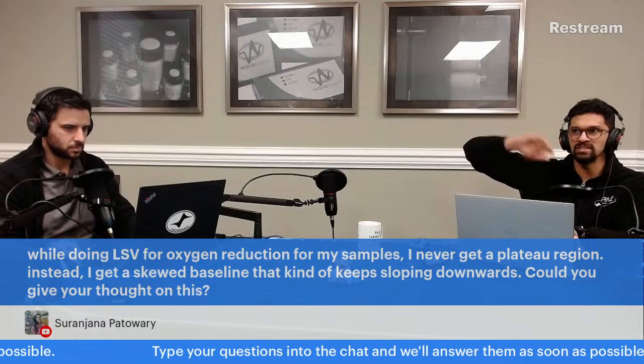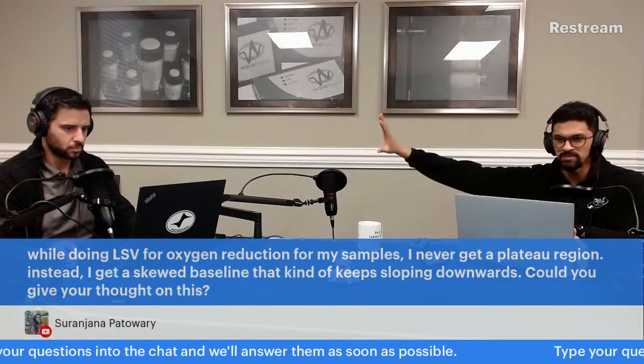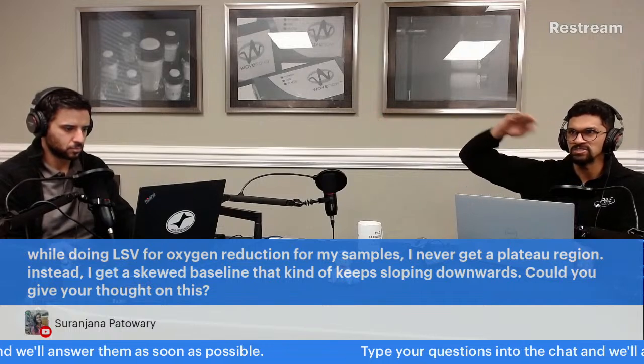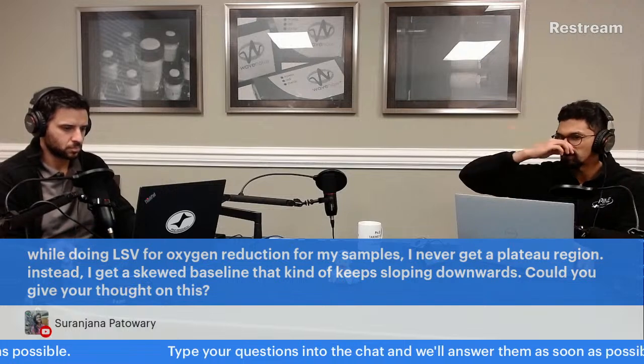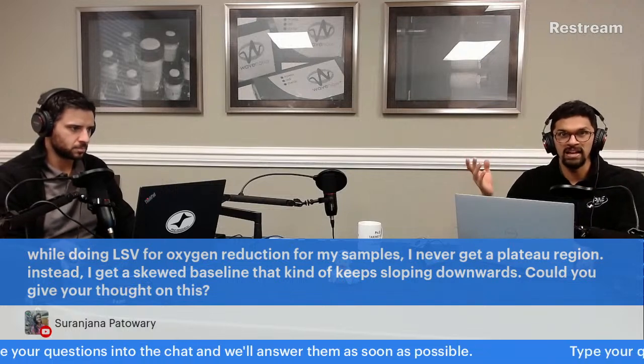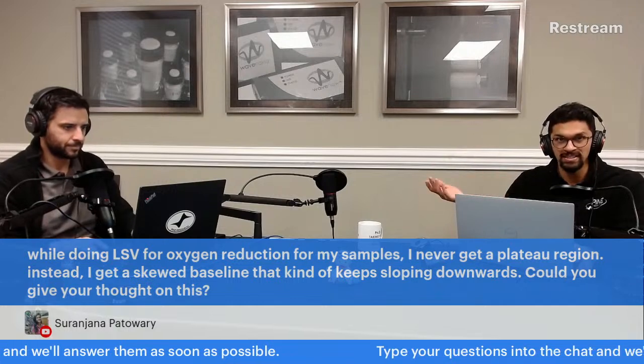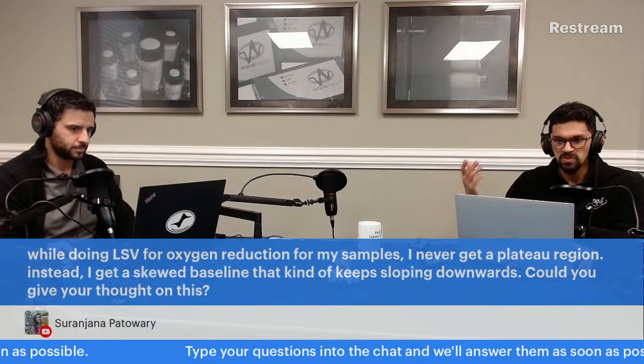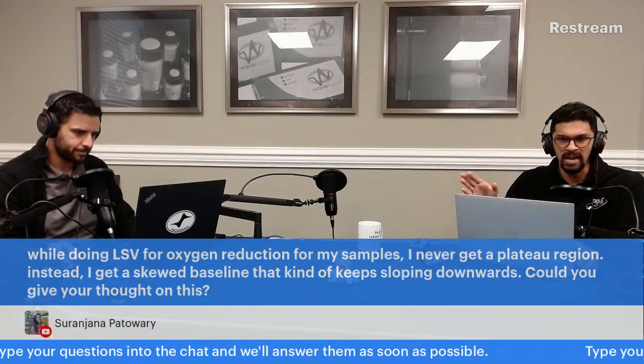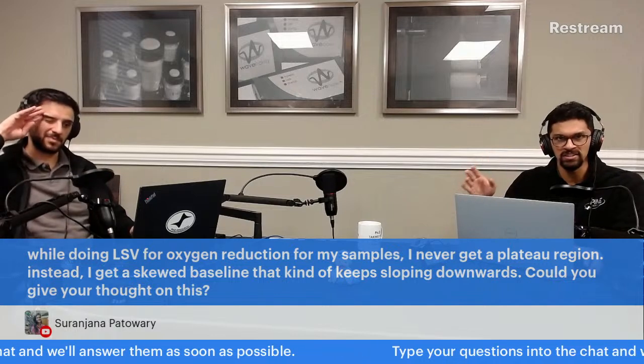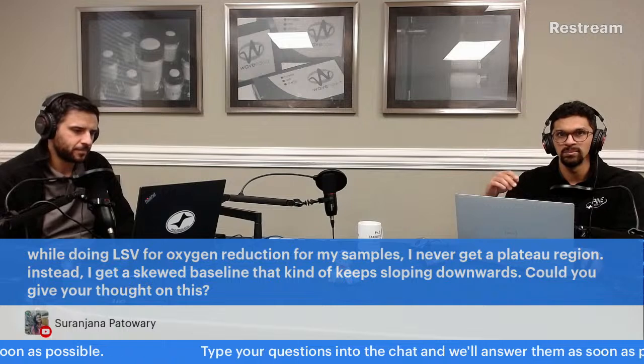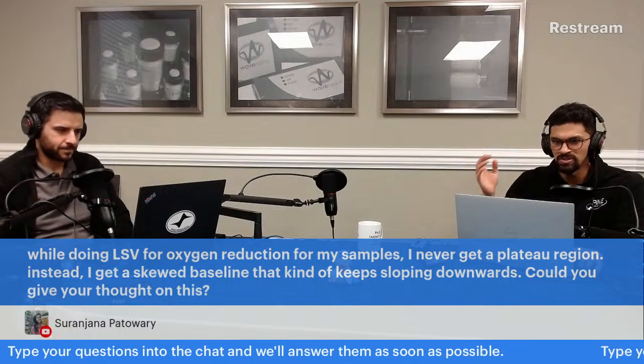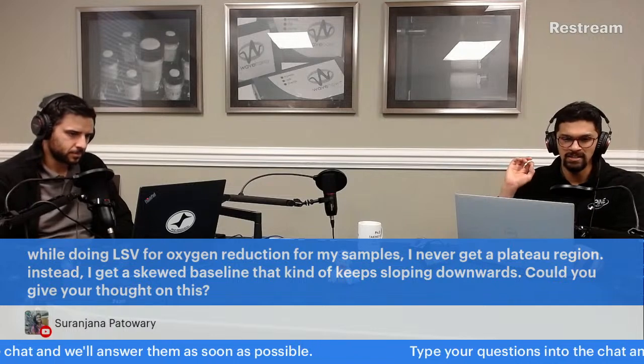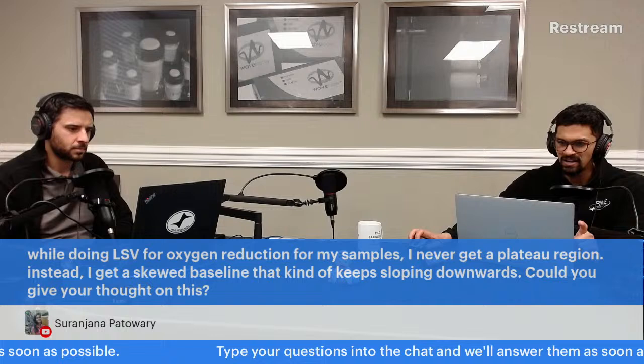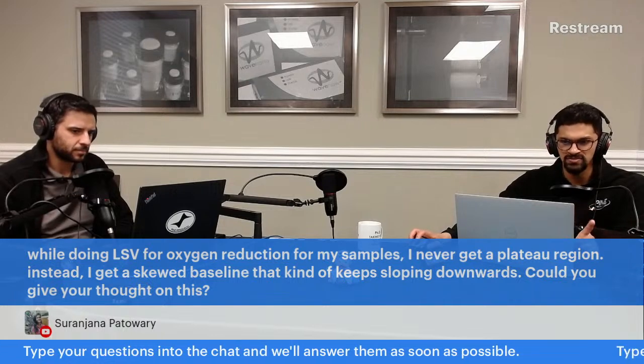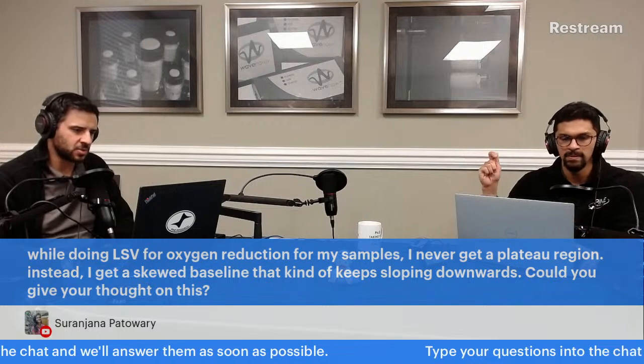LSV tends to keep curving. Are you just saying you're holding your LSV way down in this direction and it keeps curving and never flattens out? Because if it's LSV, you might not ever get a perfectly flat plateau region when doing the oxygen reduction reaction. That only really happens with RDE of the oxygen reduction reaction, or RDE in general, where you have mass transport control. So if you're listening, please clarify whether you're talking about RDE or LSV for this question about a skewed baseline. It really matters whether you're rotating or not.